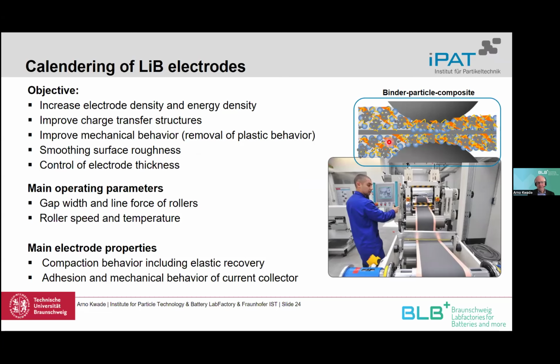Before I go to the dry coating: calendering is a really mechanical compaction of the electrode, to come from freeways between the particles to smaller streets and to have less volume for the same capacity. That means we can increase electrode density, and by that the overall energy density. We can improve charge transfer, especially the electronic transfer. The ionic transfer usually gets worse. It improves the mechanical behavior. The electrode gets much more elastic, which is really good for handling. We can smooth the surface and control the thickness, and that we do by the force coming from this roller acting on the electrodes.